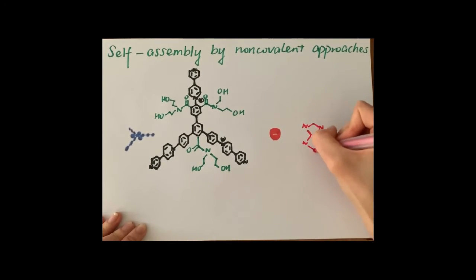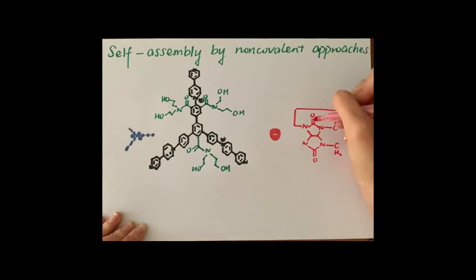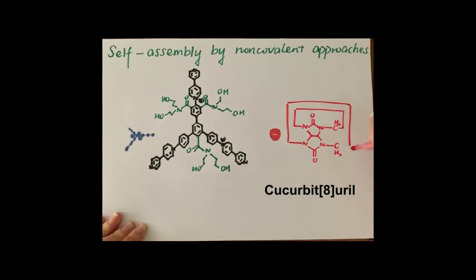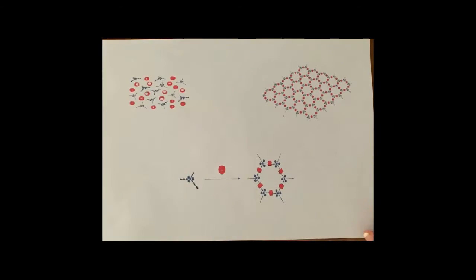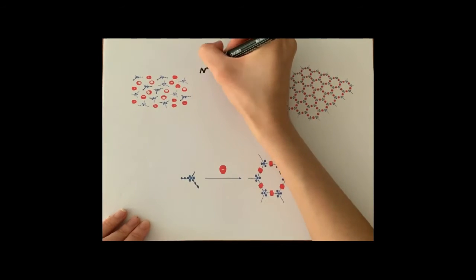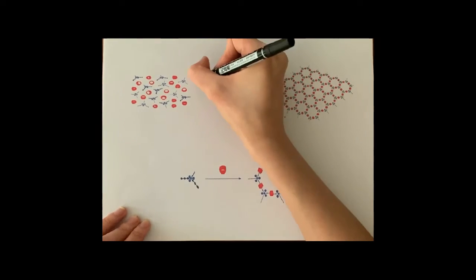By mixing the structure with CB8 in water, a monolayer 2D framework was successfully obtained in the liquid phase, driven by pi-pi stacking of 2 independent BP units in the cavity of CB8.